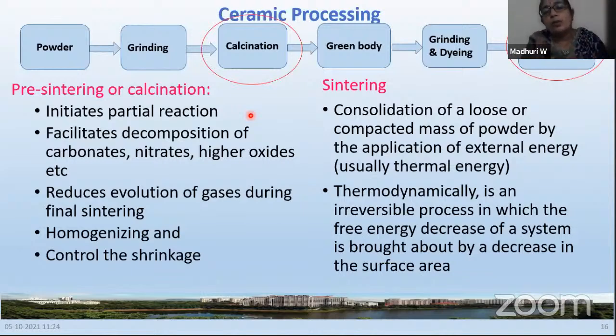Fine. So in order to avoid all that, you can go for a low temperature heating of your materials at a certain temperature for a certain time. That would take away certain mishappenings that may happen at the final sintering stage. Like these, you can read them here. It will initiate the reaction, facilitate decomposition and evaporation of carbonates, nitrates, higher oxides, and any gases which are there, and then it can homogenize and control the shrinkage. It will also control the shrinkage percentage. As you heat up, the material may shrink, and this shrinkage can also be controlled when you go for a two-step heating process. Fine.